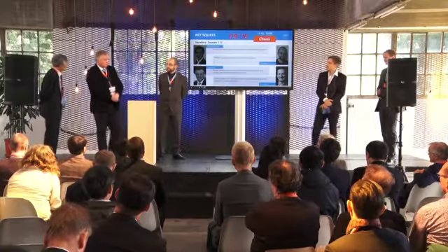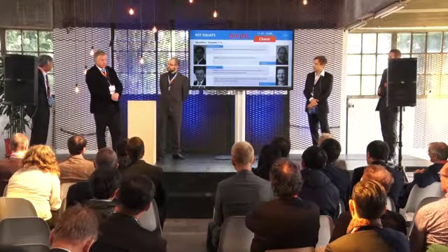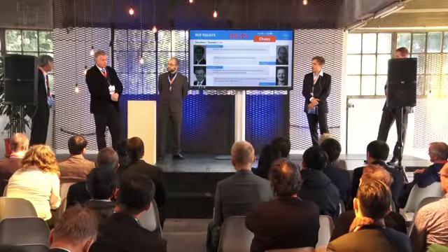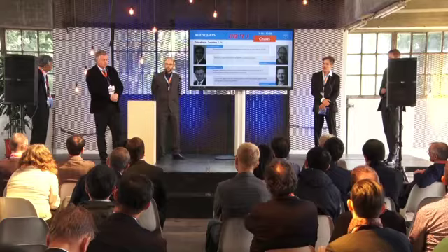I think it's a very complex problem, as we also have seen in Richard Stock's presentation, and that it's not just white etching layer which causes squats or studs. I think in the majority of our situations, we have found white etching layer and squats at the starting point. Invariably, when we pull the squat to bits, the white etching layer has disappeared, which we think has happened in the initial crack and then fracture of the surface material. But in looking at the mechanics of the situation, I think white etching layer plays an enormous role in the situation.